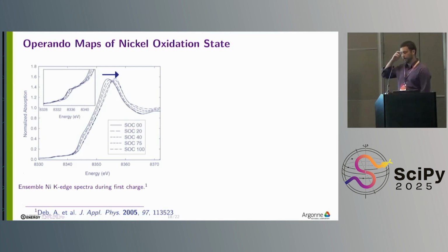So what they're asking about is there's a new phase that often forms between the electrolyte and the electrode material, but it tends to form from a combination of lithium and carbonates and things like that from the electrolyte. And so it's hard for us to see because low Z elements are almost transparent to X-rays. But in theory, yes. It depends on what it's made out of.